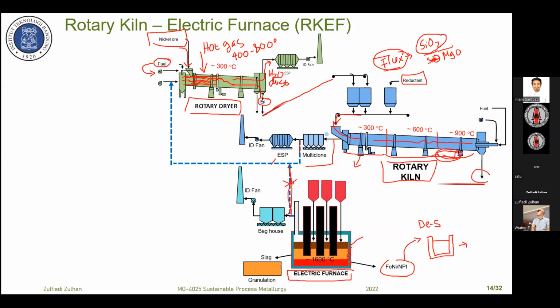And the product is calcine, and this calcine will be filled into one container. This container is lined with refractory, and then this container will be transferred to the silo or to the bin of the electric furnace by crane, and later on this material flows by gravity into the furnace. The temperature in the furnace is around 1600 degrees, and then you can get slag, and you can get ferronickel.